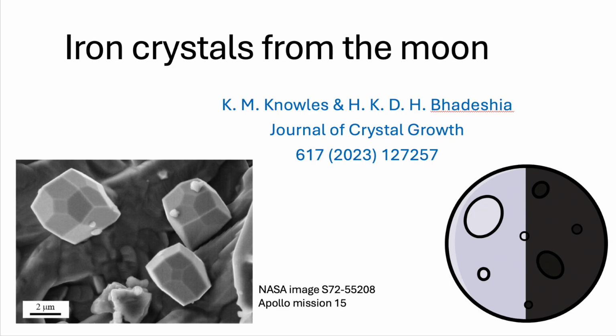So the kink sites are the atomic landing pads. Perfect analogy. Now imagine there's some trace element in that vapor and absorb it. Maybe silicon, maybe oxygen, we don't know for sure. If that impurity preferentially sticks to certain types of crystal faces, maybe the simple faces, it blocks those landing pads. Exactly. It acts like a highly selective atomic roadblock. If the impurity gums up the works on the low-index faces, it slows down or even stops growth in that direction. And if growth is blocked on the simple faces? Then the crystal is forced to grow faster in other directions, developing these steeper, more complex, higher-energy faces, like the exotic geometry we see. Growth just proceeds more rapidly where it isn't blocked.